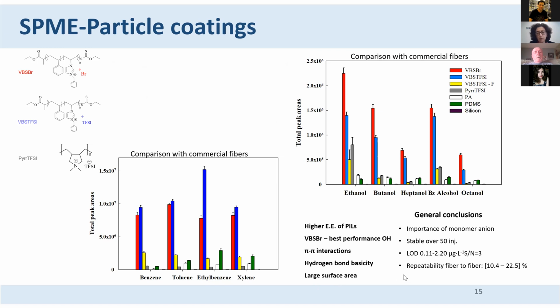The bad thing, or the problem, about these fibers was really the repeatability, because as you can imagine, each time we use the fiber, we would lose some of the particles, and that would affect the performance of the fiber. So here it was only stable over 50 injections, we could not go any further.